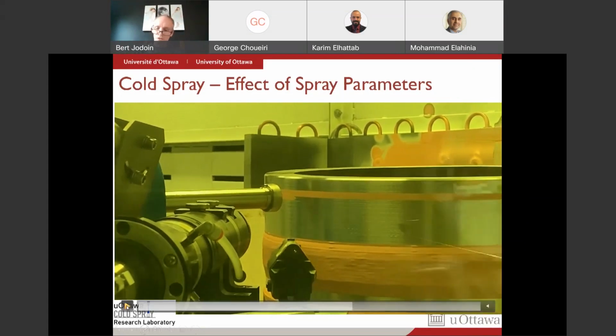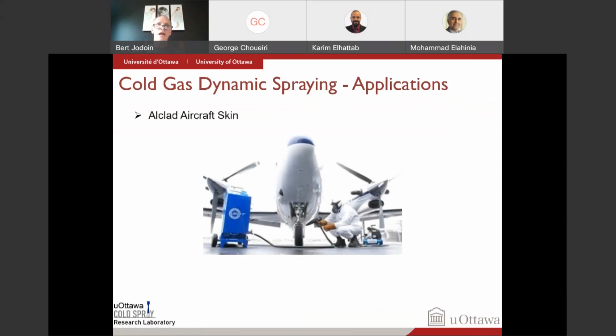Okay, so time is flying, so I'm going to try to accelerate a bit and show just a few applications. One of them is the repair of Alclad aircraft skin that was done in collaboration with Boeing. So the aircraft skins are usually made out of Alclad, so that's an aluminum alloy, and on top of it you have pure aluminum to protect against corrosion. And sometimes you get these surfaces damaged, and the way to repair it for them was to take out the panel, strip the full panel out of its aluminum, and then reclad it, which is very time consuming and very expensive. So by using cold spray, we can have a portable cold spray system where we go and we spray directly. So we just grind a bit out where the damage is, and we spray right there the pure aluminum coating, and we polish it, and there you go.